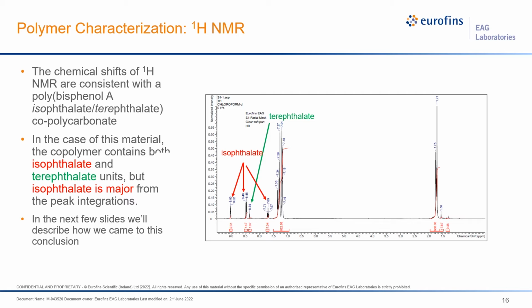Consulting the literature once again, we were able to successfully identify the polymers that are present in this sample using NMR. This material is consistent with a polybisphenol A isophthalate terephthalate copolycarbonate. We have three peaks that are labeled red that are due to the isophthalate residues, and we have one peak that corresponds to the terephthalate. We can see that there's some differences in the signal intensities, so right now we would believe that the isophthalate seems to be the major species with respect to the terephthalate.